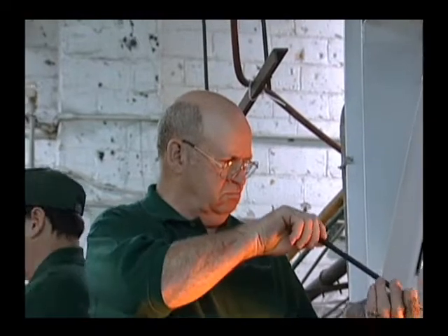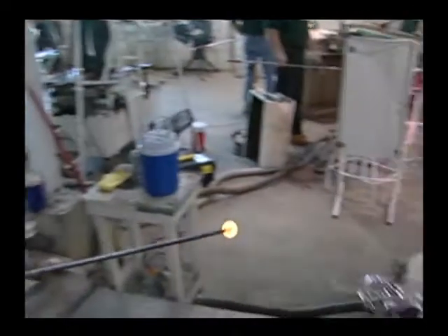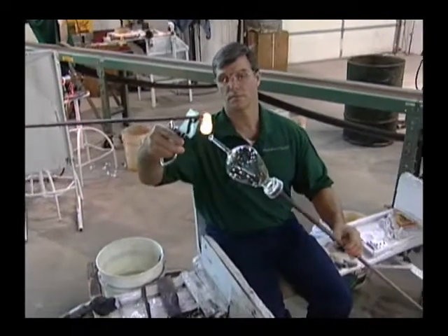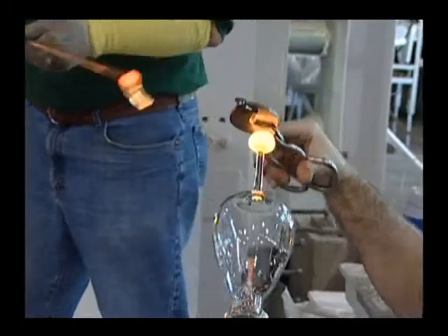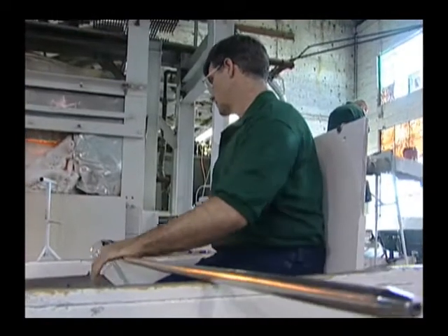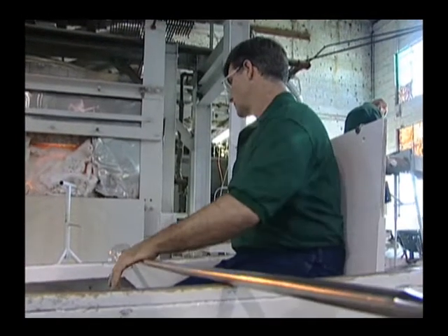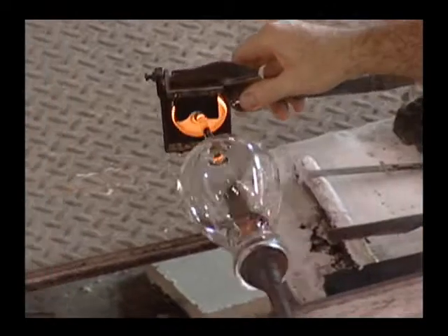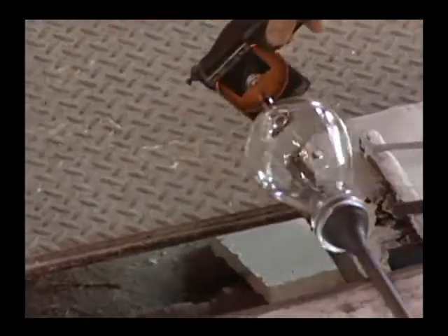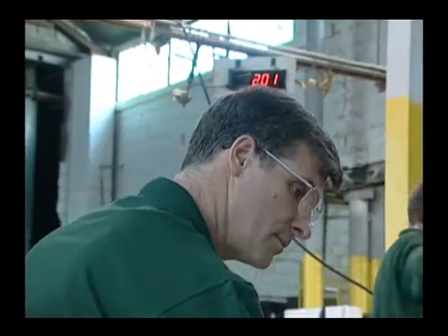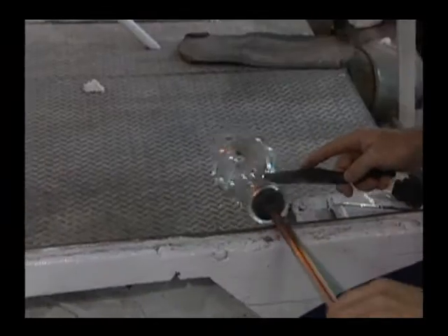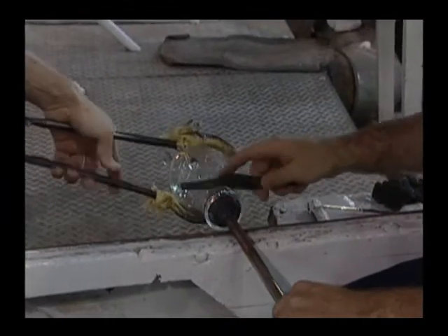The foot gatherer shapes the correct amount of molten glass on a rod called a punty. After shaping the glass, the foot gatherer presents the glass to the stemware finisher, who applies the molten gob to the end of the stem. Again, the glass must be constantly rotated to avoid runoff. Using a tool called a clapper, the stemware finisher rolls the foot out to the exact size, aligns the foot to the stem and bowl, and cracks the fully blown piece from the blowpipe.